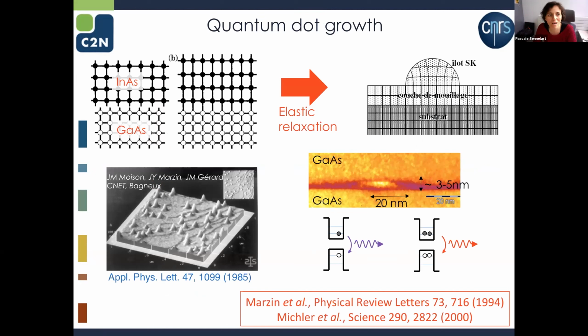So now let's have a look at what is my emitter, my quantum emitter. In the same growth step, I will now grow indium arsenide on gallium arsenide. And it's very different from what we were doing before, because now these two materials don't have exactly the same lattice parameter. So when I try to grow indium arsenide on gallium arsenide, the material tries to conform to the host material, but there is a lot of strain stored here. And at some point, the system relaxes to minimize the energy, and you obtain this kind of nano lenses that actually form a nanometric trap for emitters.